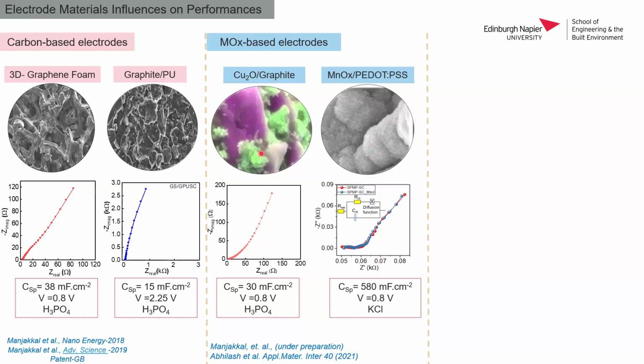In the first versions, these 2 versions, the graphite polyurethane and the Cu2O, we use thick film technology. In another version we use the electrochemical deposition method, where nanoparticle or more oriented material is forming, and which enhances the performance.